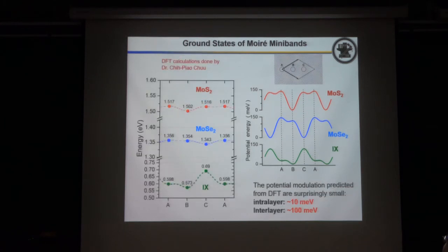We also try to use DFT calculation, and what we found very interesting is that our experimental result predicts that the potential modulation could be up to 100 millielectron volt, but the DFT calculation only predicts very small potential modulation. I think there is still some discrepancy because in the DFT calculation, we didn't consider the structure reconstruction because this is a lattice mismatch system. They may have some strain at the different high symmetry points in the moiré supercell.